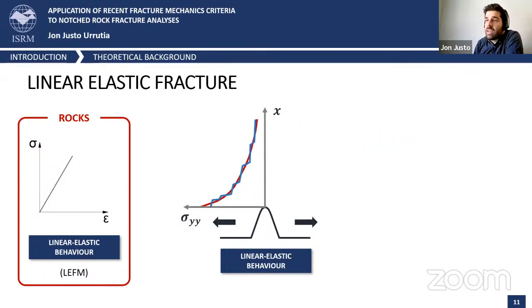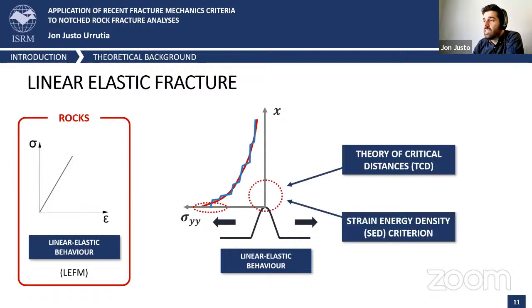In any case, neither the theory of critical distances nor the strain energy density criterion consider the maximum stress just at the notch tip, but they evaluate what is happening in front of the defect tip, not only at the tip. So these conditions somehow absorb the difference between the smooth and the stepped curves.